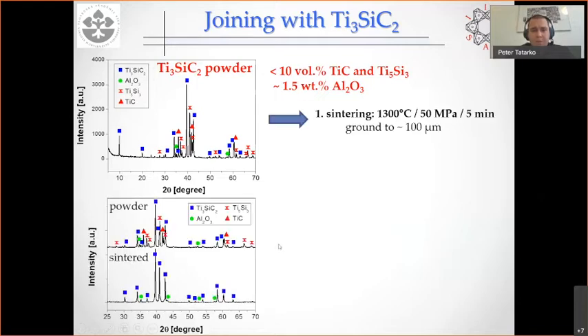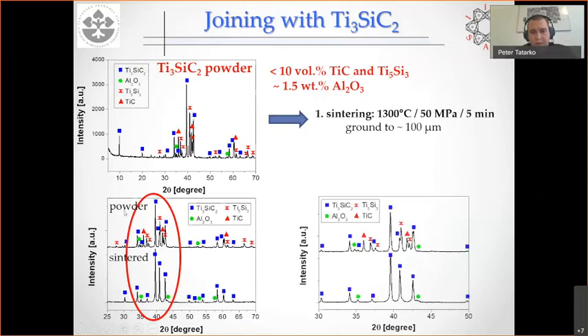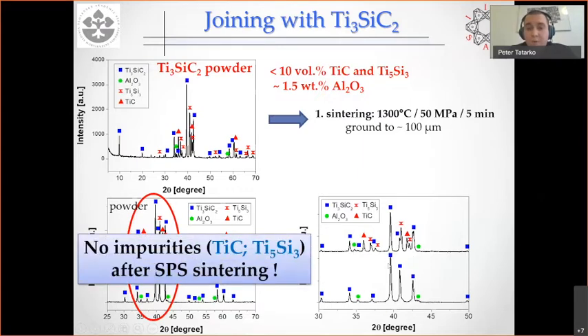And what happened was very interesting. You can see here, this is the initial powder, and this is after SPS sintering. Here, this graph is zoomed in. And what you can see, after SPS sintering, all these peaks referring to the impurities vanished. We didn't see any titanium carbide and titanium silicides anymore. It was very important for us because, in other words, we used pure MAX phase for joining, of course with some alumina, but as I explained before, we wanted alumina to be in there.